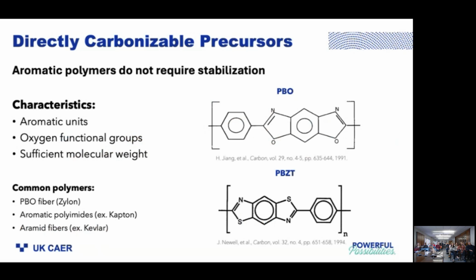There are, though, interesting glimpses of the future. These are directly carbonizable polymers, and you can make fibers from these. These are kind of like Kevlar fibers, the polyaromatic or polyaramid type fibers. PBO is polyparaphenylene benzobisoxazole over here. We can spin fibers from this, which we can convert to carbon without doing oxidation at all. You just basically heat them to carbon and you're done. Cut out those hundreds of minutes of oxidation. Same with the PBZT, which is the sulfur analog of PBO.